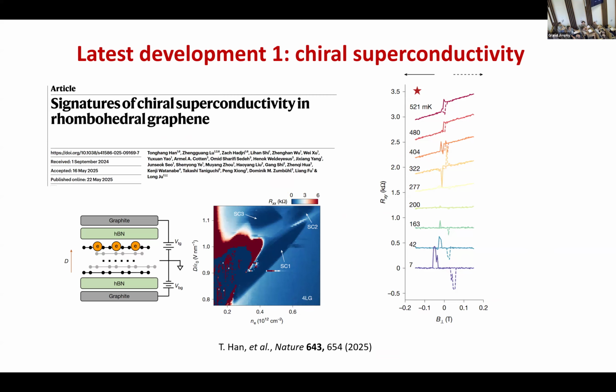Actually, the difference between this and twisted bilayer graphene is that in twisted bilayer graphene you have this magic angle and you have the AB domain aligned. And here you have a multi-stack with three different alignments and then you repeat the structure. Because I want to just quickly go through this, this is a four-layer graphene. ABC, and the other one is another stacking along this way, ABCA.